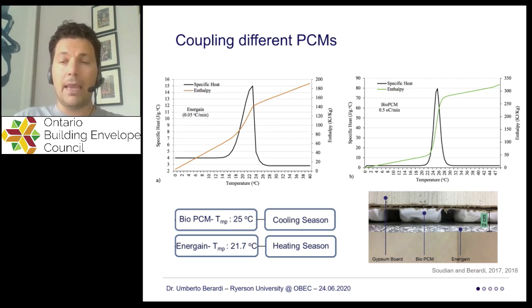I said before to pay attention to the temperature, and the reason is that the PCM does this kind of phase change transition, but it's critical to understand at which set point we typically use our thermostat. A good starting point for saving energy is probably to have different set points for heating and cooling, particularly a cooling season temperature set point in the range of 24 to 27 degrees, and probably for the heating season from 20 to 22 degrees Celsius as the set point of your air conditioning system.